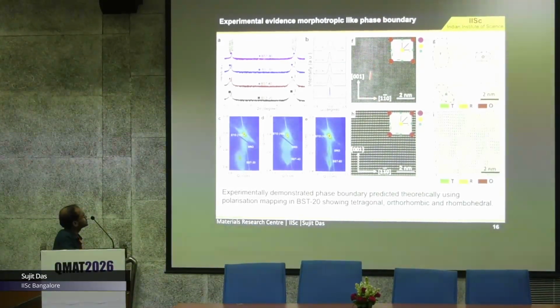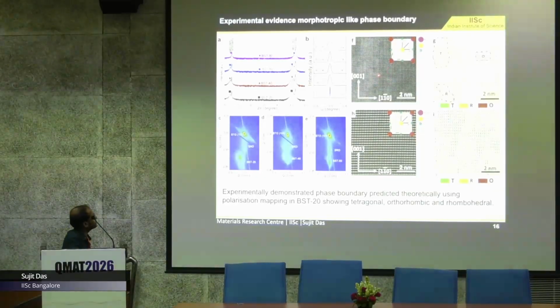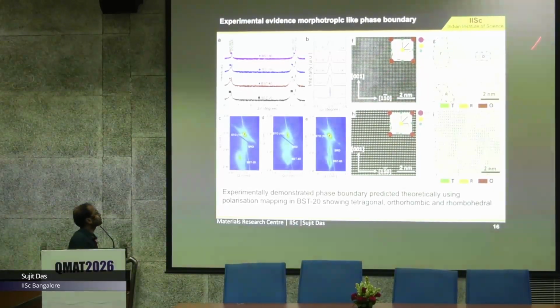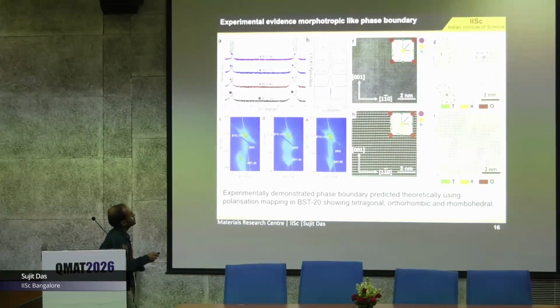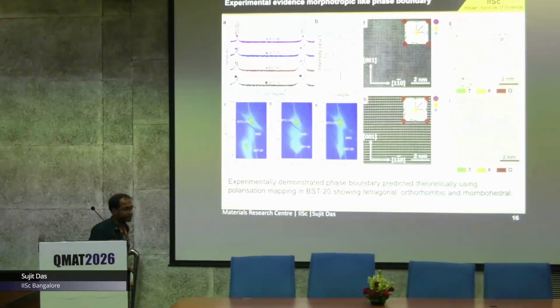This is the cross-sectional transmission electron microscopy for the BST20 and the corresponding polar mapping, showing a mixture of the tetragonal, orthorhombic and rhombohedral phases. If we take the BST60, we can see it has only a single phase, a tetragonal phase.